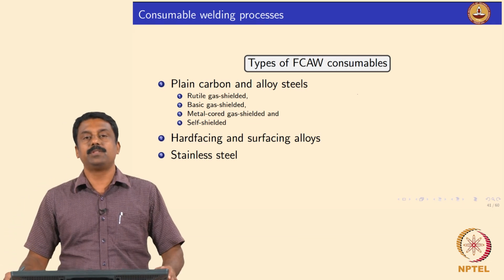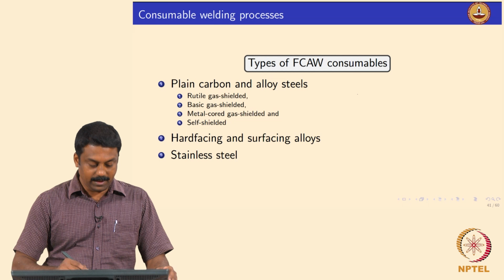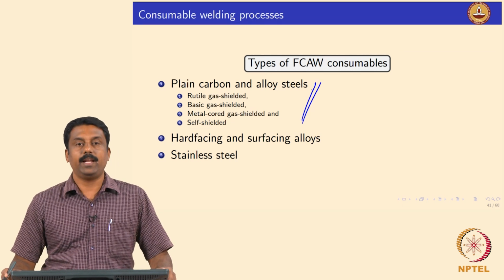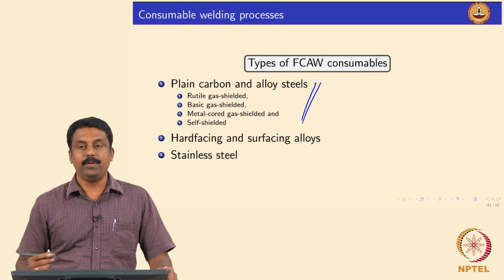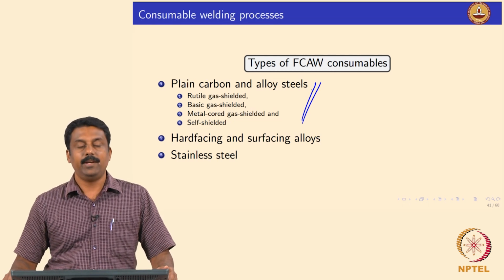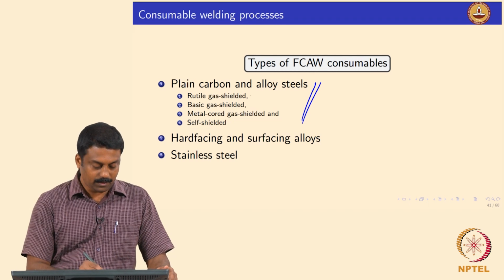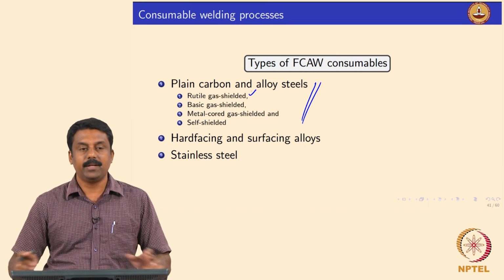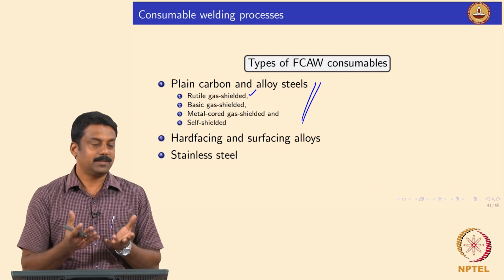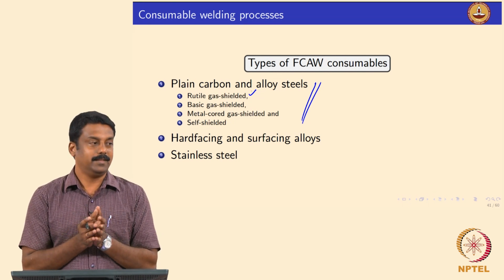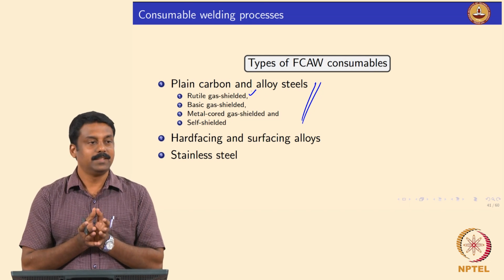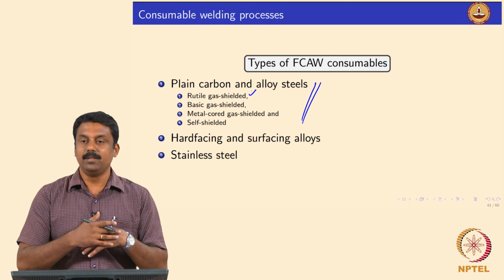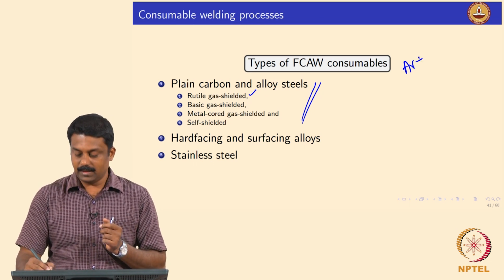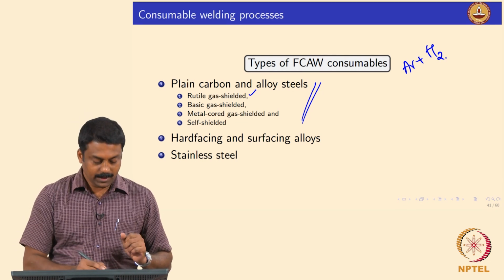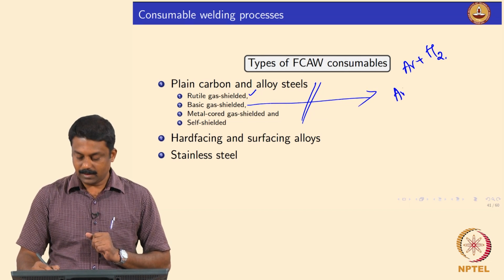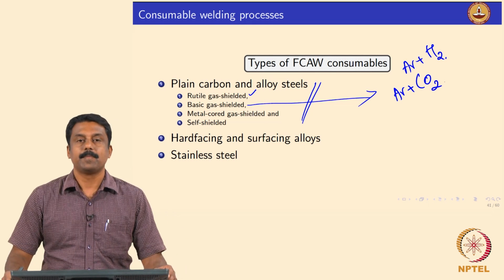So, what are the types of commonly used flux cored arc welding electrodes? So, I said for plain carbon steels, we have rutile. If you use rutile, obviously if you do not have enough flux to generate shielding gas, you need external shielding. So, rutile electrodes with gas shielding. That means you need to have an argon cylinder if you want to use argon. So, then it becomes argon plus hydrogen shielding, is it not, because rutile can generate hydrogen, and then argon can come from the bottle, and then the shielding would be argon plus hydrogen, right. The basic gas shielding will be argon plus CO2, right.